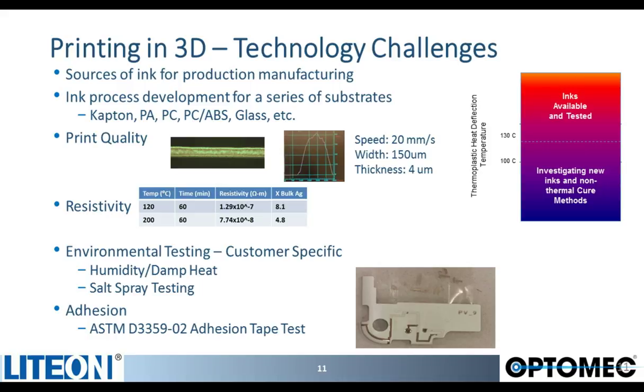As an example, for some customers, the printed antenna needs to survive high humidity and temperature cycling between 25 and 55 degrees centigrade in 9 cycles for a total of 6 days, as well as salt solution sprayed directly on the product for 2 hours, and then left in high humidity for 7 days. And after this test, we check for functionality and adhesion.